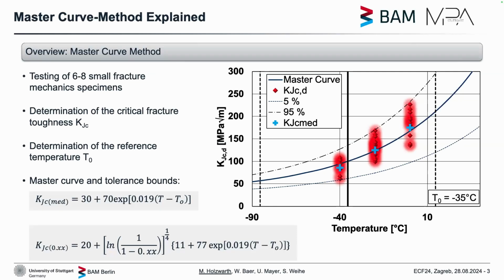And the master curve concept is then valid for the temperature of plus or minus 50 degrees around this reference temperature, which are then this area. It's currently already used for the safety assessment in the nuclear safety department for pressure vessels, for example, as supplement to the ASME reference concept.